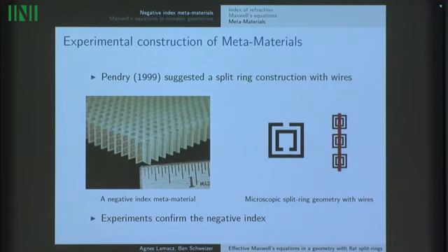namely by Pendry and his group. Of course, this artificial material has to be artificial because materials in nature don't have this property. It has a fine microstructure consisting of many small, flat, periodically distributed rings, or double rings in this case, with a very thin slit, so-called split rings. And the split rings are made of a very highly conductive material. Moreover, very thin, highly conductive metallic wires are running through the rings, as indicated here also in the sketch.